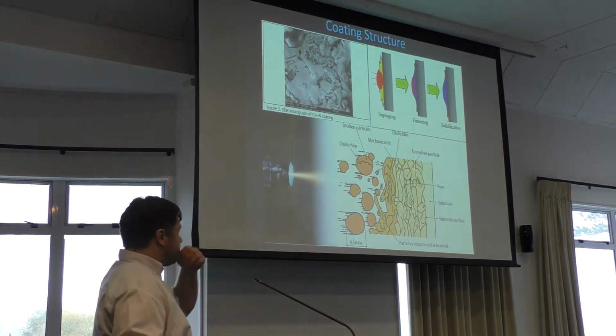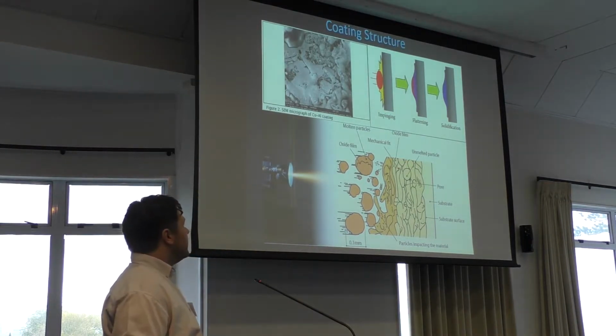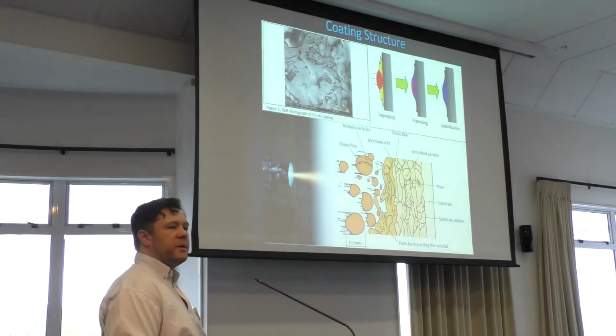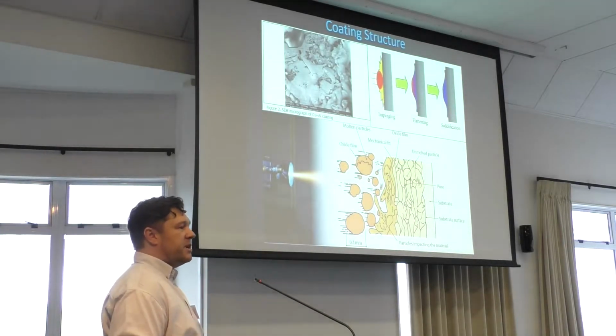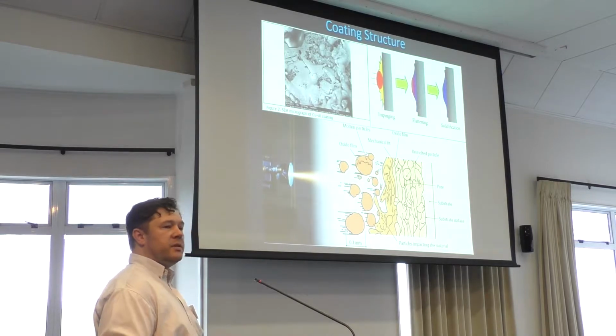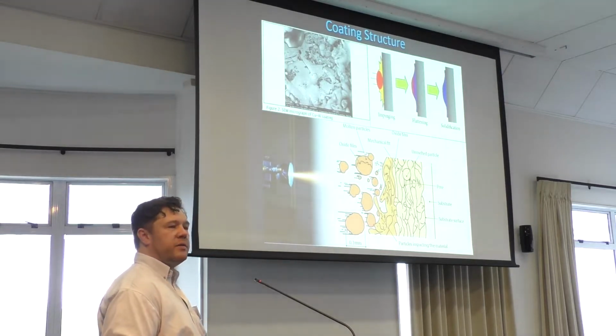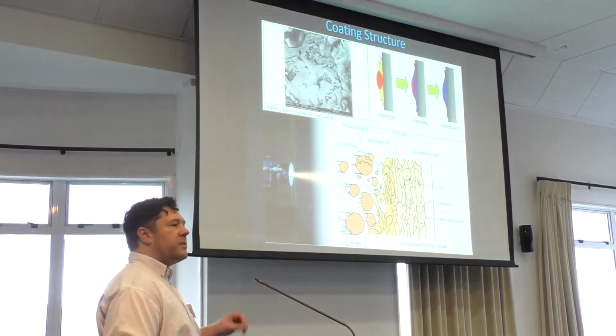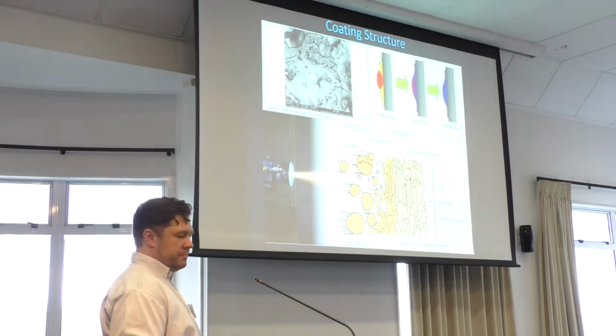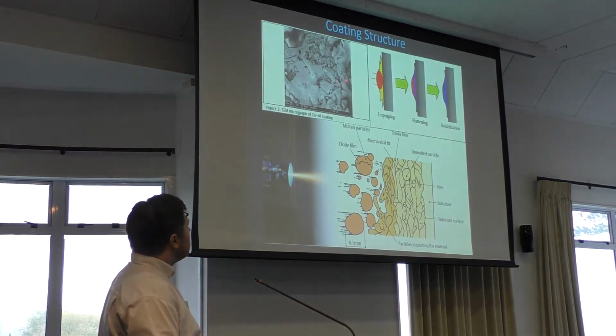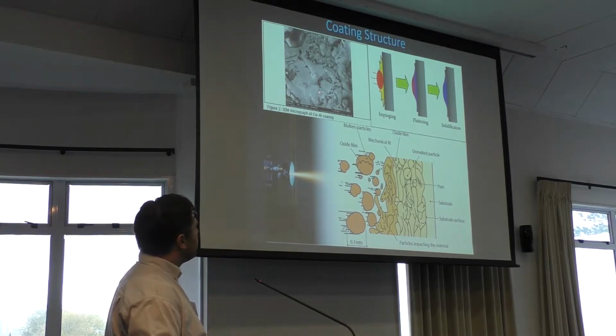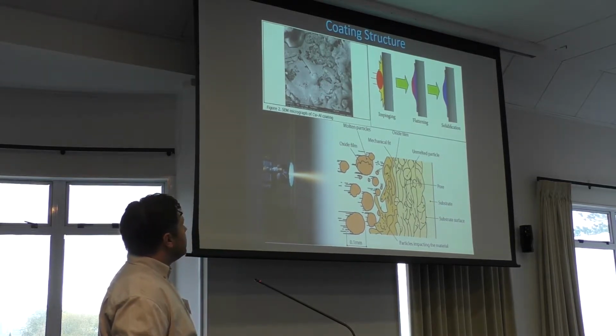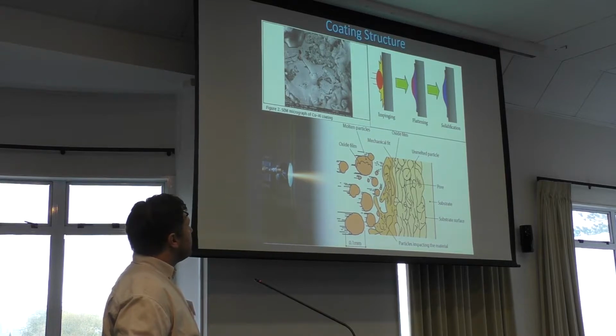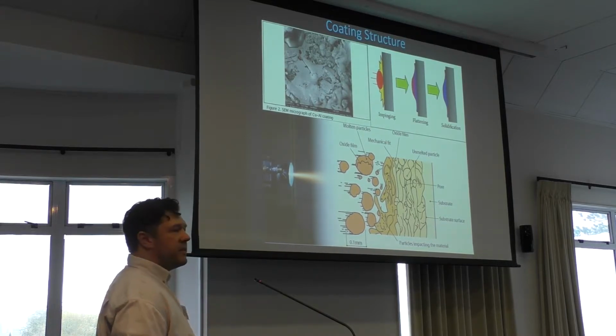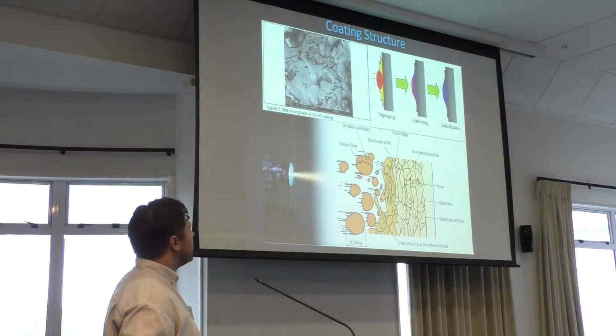So the coating structure. Basically, there's a stock material, whether it be wire or powder. For the zinc and aluminium, it's typically a wire. It's molten either through a flame or through an arc process, and then compressed air atomises that melted wire and blows it at the job so that we create a coating. So here's just a SEM micrograph of a zinc aluminium coating. So it's pretty highly magnified in there, and it doesn't make much sense to us to look at. I'm going to go a little bit deeper into that later.